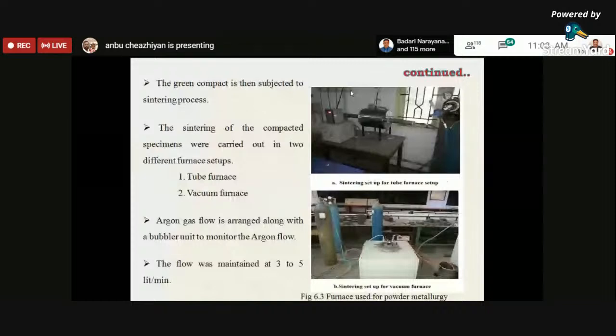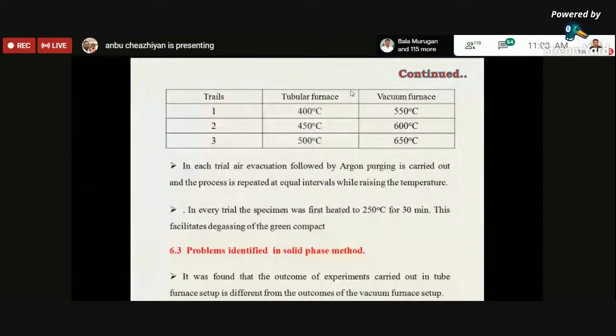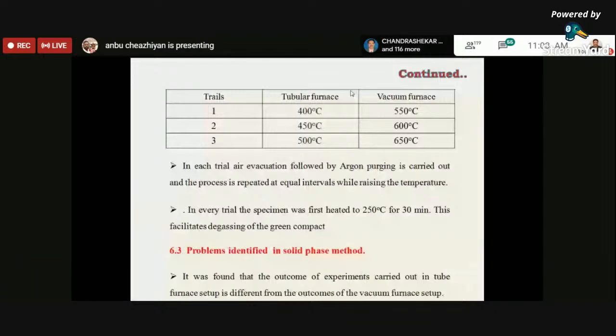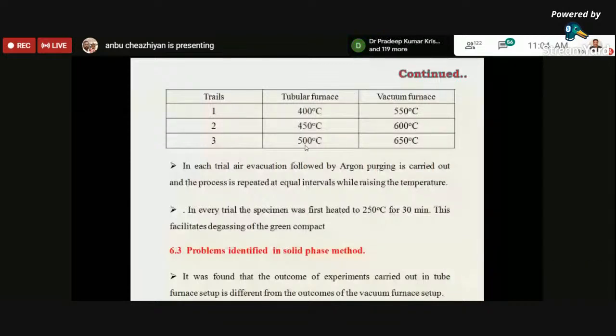Three trials were made with the tubular furnace and the vacuum furnace. In the tubular furnace, first we went for 400 degrees centigrade. In each trial, air evacuation followed by argon purging is carried out, and the process is repeated at regular intervals while raising the temperature. In every trial, the specimen was first heated to 250 degrees for 30 minutes for degassing the compacts. We made three trials: 400, 450, and 500. Similarly, we increased the temperature to 550, 600, and 650 degrees centigrade.